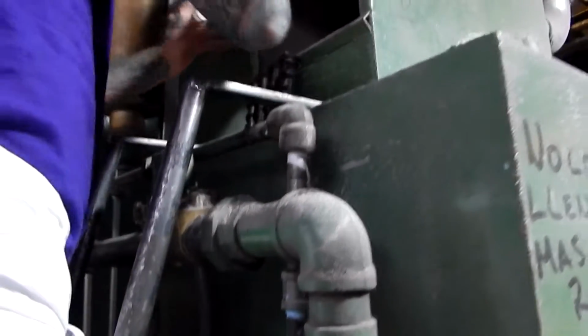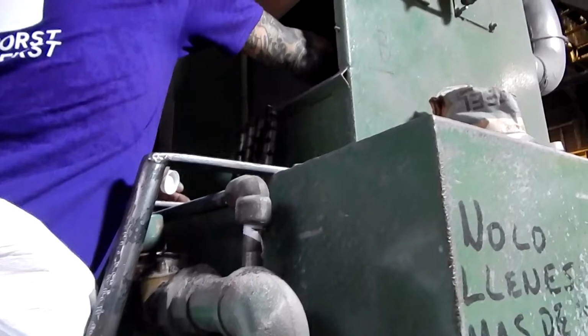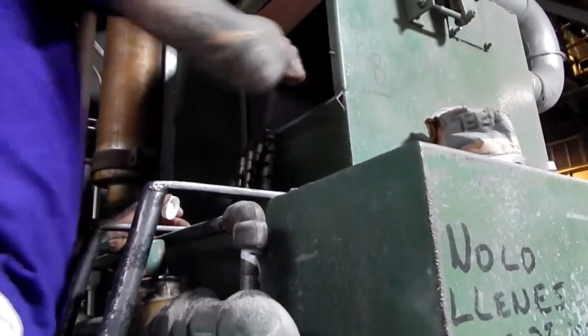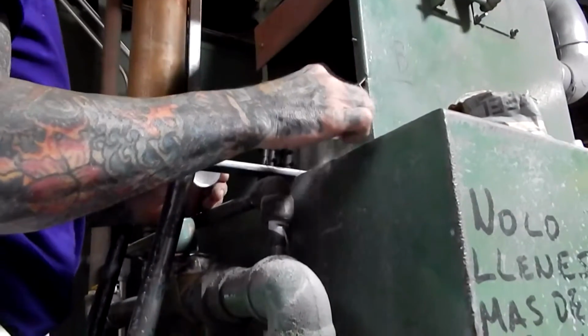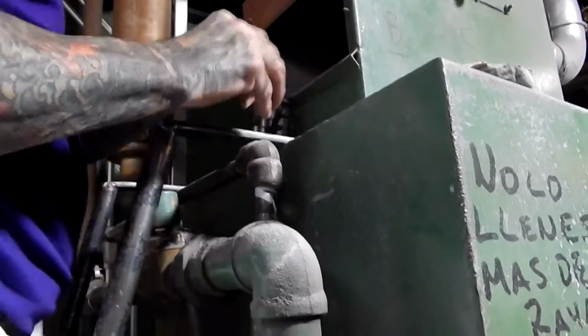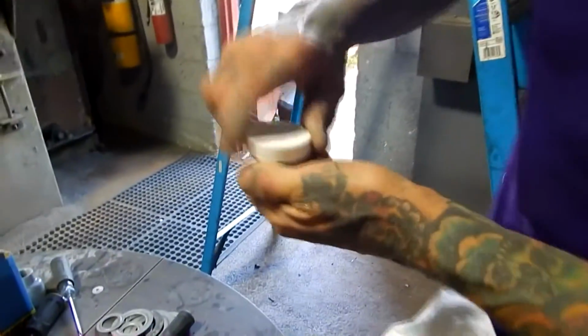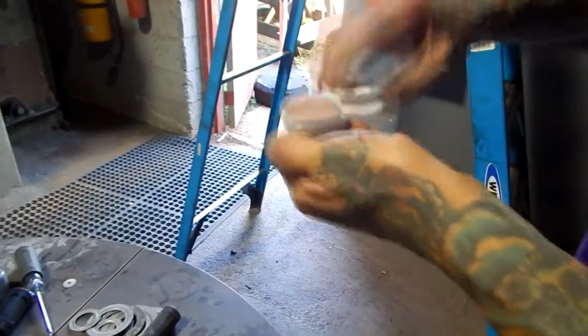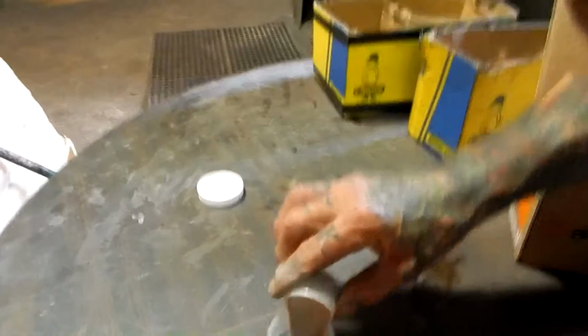Step 2. Perform abrasive test. This test is completed on the garnet that is used to blast the pieces. In accordance with the SSPC standards, the acceptable result of the test is to be less than 5 ppm. Pick out the small cup with the lid and remove the lid. Fill the cup with blasting materials. Pour the blasting materials from the small cup into the water-filled cup with lid.